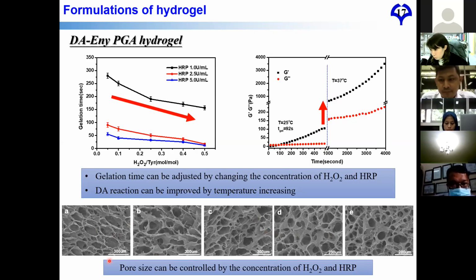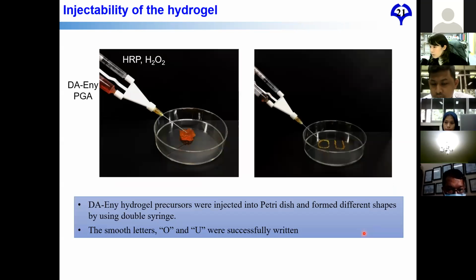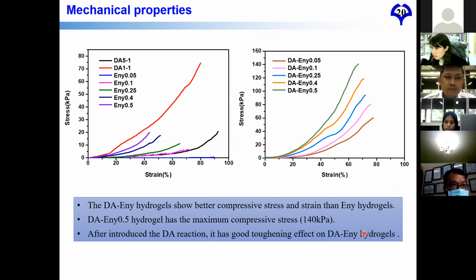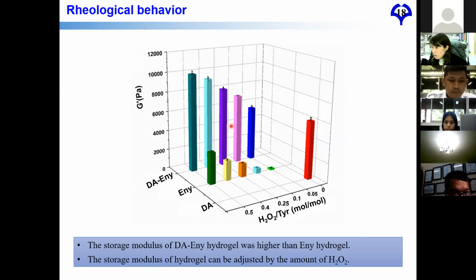If we see the SEM structure, if we increase the cross-linker in the hydrogel, the pore size will decrease. Okay, this is also about the storage modulus. If only using the enzyme, the storage modulus is very low. And using the Diels-Alder reaction, we can increase the storage modulus of the hydrogel.